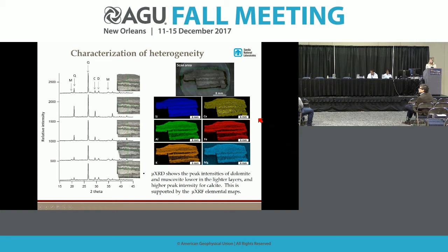And this is supported by our elemental mapping. We use micro X-ray fluorescence to map elemental composition. I'm showing silicon, aluminum, potassium, magnesium, iron, and calcium. As you cannot see, but trust me, silicon is homogeneously distributed because there is roughly the same amount of quartz throughout. But aluminum, potassium, magnesium, and iron are more concentrated in the darker layers. So there's more dolomite, as we saw with the X-ray diffraction, and muscovite in the darker layer. And calcium is brighter in the lighter layer, so there's a little bit more calcite in that lighter quartz-rich layer.